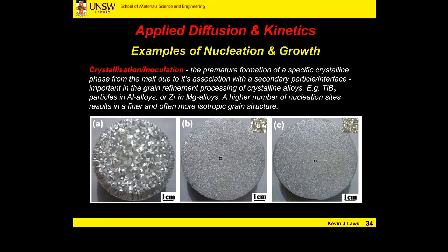However, when we add the inoculant, we can see straight away a dramatic change in the microstructure. We've got multiple tiny equiaxed grains. In terms of mechanical performance, what does the smaller grain size mean? Higher strength. What does a non-directional orientation of a grain mean? So we've got isotropy, rather than a casting texture.